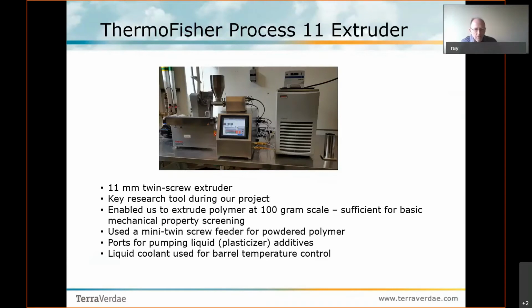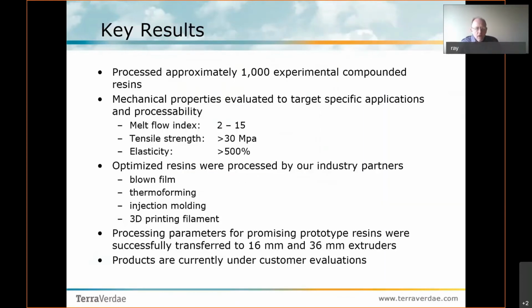We had a mini twin screw feeder for the powdered polymer, and a port for pumping liquid plasticizer additives as we needed. And then we had the coolant system so that we had good barrel temperature control. The main results on the technical side: we processed probably close to 1,000 experimental compounded resins over the past year and a half, and so we used this machine a lot.